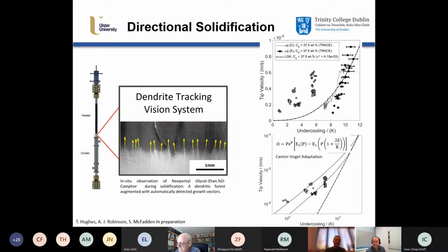Well, here's some work. Obviously, tip velocity versus undercooling is of interest. To give you some background, you see some data points here that were available through microgravity experimentation. This was done through the TRACE experiment, all at reasonably high undercooling, 7 Kelvin and above, both columnar and equiaxed. The reason it's at such a high undercooling is because it's microgravity sounding rockets and it's time limited, so they had to grow fairly quickly to get something reasonable within the time frame. That left a gap in the knowledge below 7 Kelvin. So we looked at trying to fill this gap, and you see the data points that we've generated here.